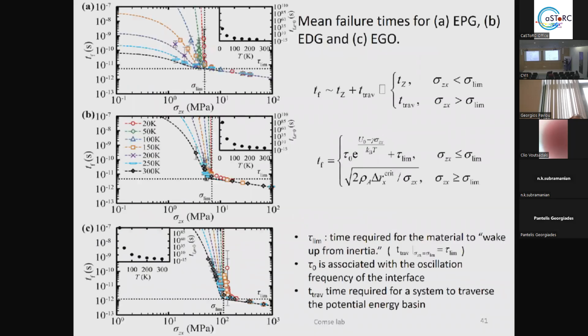And this we can see here for all the three different systems: the epoxy pristine graphene, defective graphene, and graphene oxide. We see that the three whole systems have this exponential behavior, and after that we have this linear behavior. Again, this here is the proposed equation that is the result of the parameterization, of course.